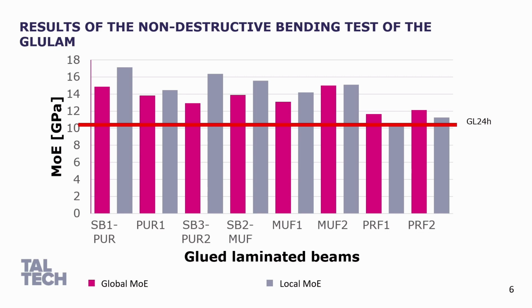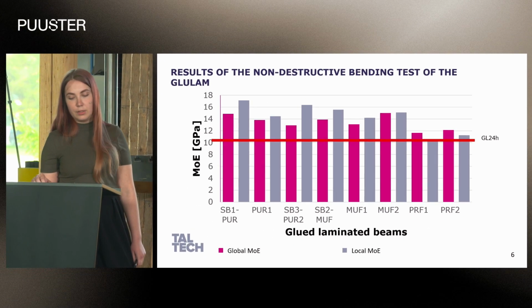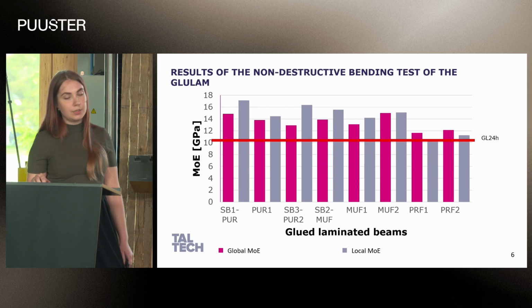This graph shows global and local MOEs collected from the non-destructive bending test of the glulam beams. All of the super beams, which were manufactured from the stiffest lamellas, had the highest local MOEs, and 6 beams from 8 exceeded the stiffness of strength class GL24H. The 2 beams that didn't were bonded with adhesive PRF, which had a much thicker consistency and was more difficult to apply evenly with brushes.